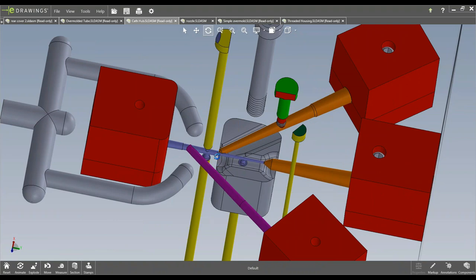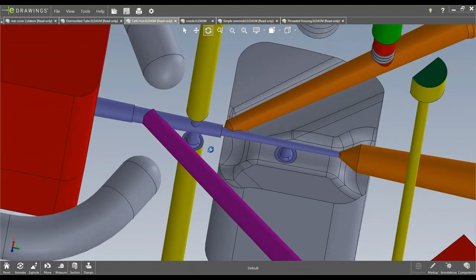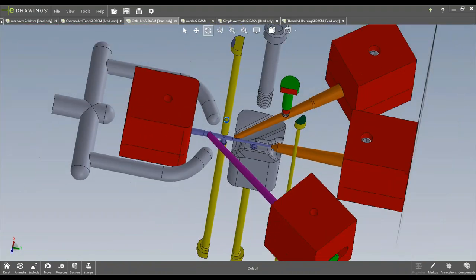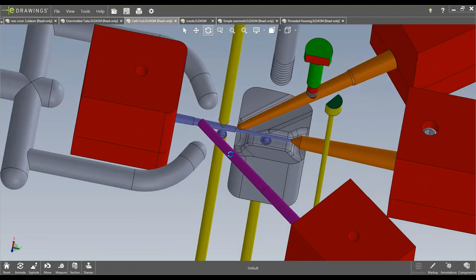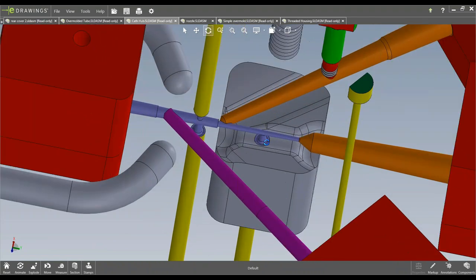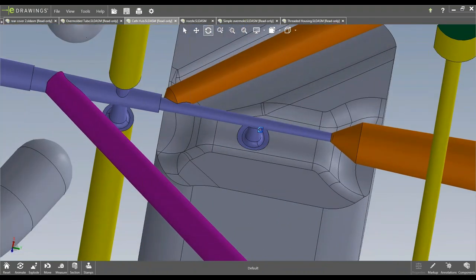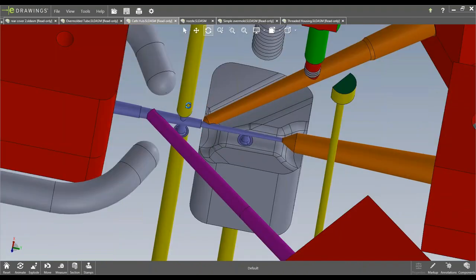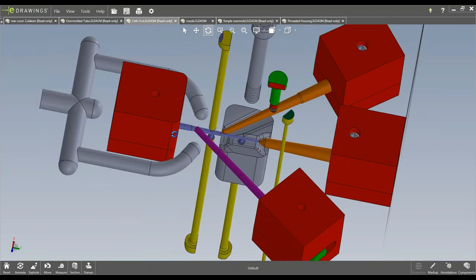And also, we've got some small IDs and we have to hold those center. So that's what these kind of yellow core pins, you see your standoffs are holding those center within the part, holding these core pins. So as the mold opens, those go away with the core and cavity. And then these parts will be pulled out after molding in a normal production setting. They'd be automated actions.